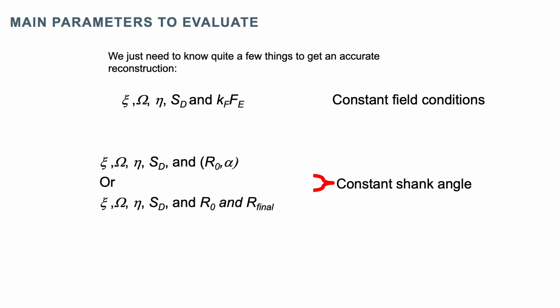So these different models just have a number of parameters that need to be defined. So the image compression factor, the field itself, the atomic volume, which has to be not the ionic volume, but the volume of an atom inside of the material initially. So it has to account for the free volume, so will depend on the crystal structure, for example, which AP Suite or IVAS never took into account. So there are quite a lot of assumptions in the reconstruction, in the way it's been implemented, that need to be borne in mind.